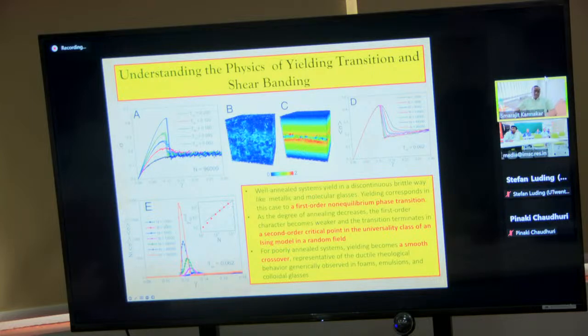It is very, very clear that as one looks at these shear bands in increasing system sizes, the stress drop, as shown in panel A, becomes larger and larger. And if you look at the corresponding susceptibility, which tells you how much fluctuation you have around this yielding process where the shear band appears, that susceptibility turns out to grow with increasing system size. And this somehow signals that there is a large length scale coming up, and this length scale is obviously connected to the spanning shear band that one sees.